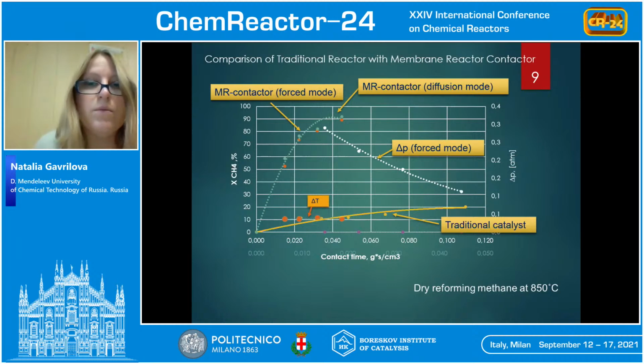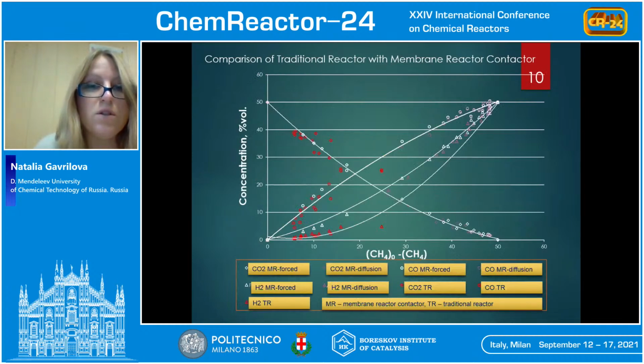The small difference in the value of the rate constant in the membrane reactor contactor with two different modes gives grounds to assume that in both contactor modes, driving forces of similar magnitude and origin act, causing the transport of reagents through the porous structure of the membrane catalyst. In order to make sure that the reaction mechanism remains the same, the following dependence was presented.